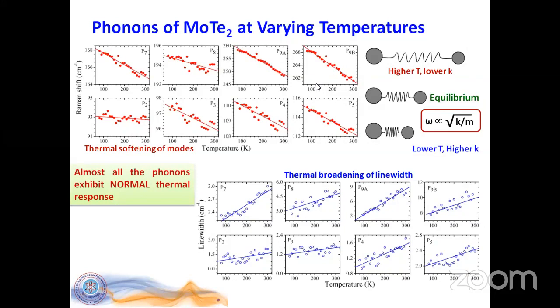Now, we also looked at various other phonon modes. As we said, there are 9 different phonon modes, and we saw that all these other phonon modes show a usual thermal behavior, which is basically the frequencies show thermal softening of the modes. On the other hand, the line width shows the usual thermal broadening, and that is typical, normal.